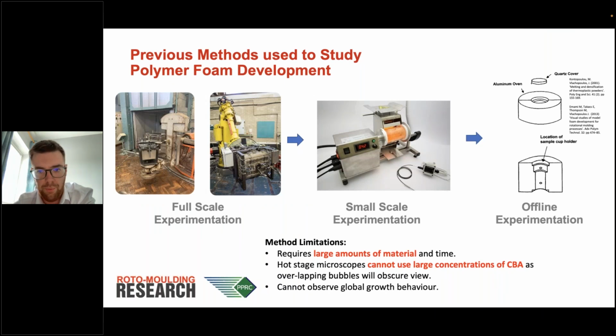So instead, what I started to explore was this miniaturization, looking at either small scale or offline experimentation techniques. The limitations, obviously, of using full-scale equipment are that you're going to use large amounts of equipment, and it can take quite a while to produce, even just a foam-only molding. On the other hand, the hot stage microscope systems, because you're imaging the polymer melt as the foam grows, as the bubbles grow in size, at a certain point, when the bubbles start to merge together, don't really give you that much information. And that means you can't observe the global growth behavior of your foam.